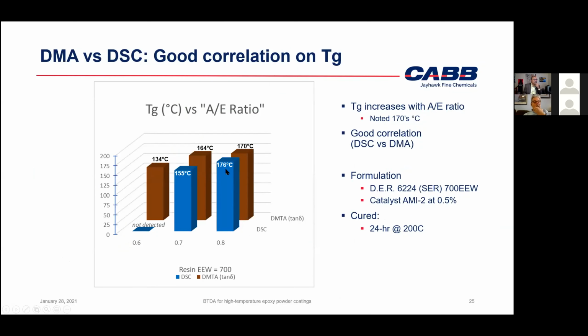That one gave a little bit higher, but more or less DSC and DMA did give us good correlation, at least in the situation where we were able to detect a Tg. So that was a good thing. At least the conditions worked out. And you can obviously see that the Tg rises steadily if you increase the amount of BTDA, or the A/E ratio, down by the bottom here.